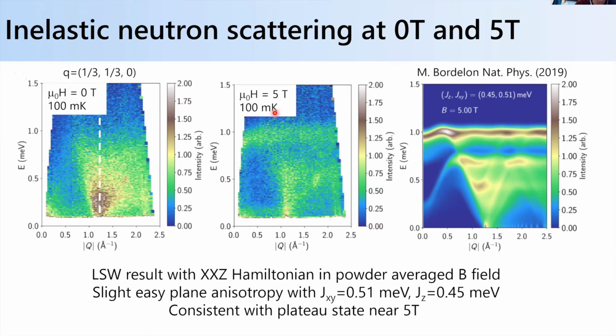And so we can then take this spectrum that we've collected under 5 Tesla, and we can try and fit it using an XXZ Hamiltonian and a linear spin wave analysis, okay? And we can just do a powder average magnetic field. And this is stuff that Qinjiao and Leon Blentz did. So basically by just doing this simple analysis with linear spin wave theory, we can get a really reasonably good match of the expected spectrum of magnetic fluctuations within the up-up-down state.